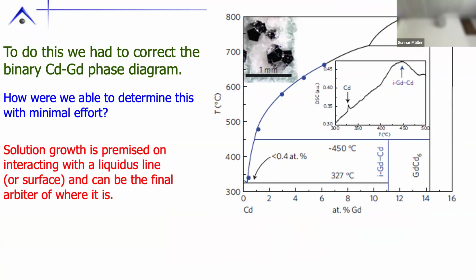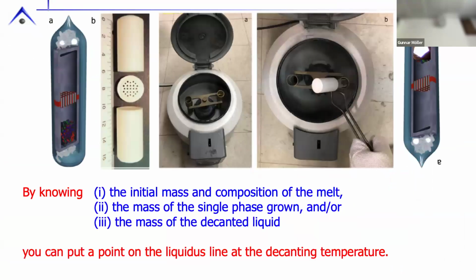Well, solution growth is premised on interacting with this line, and it can actually be the arbiter of where it is. So this is going back to the question of how do I control what my growth is? By putting elements into the crucible. If I know the initial mass and composition of the melt, and I can measure the mass of a single phase grown or the mass of decanted liquid of a single phase grown, I can put a data point on the liquidus line.